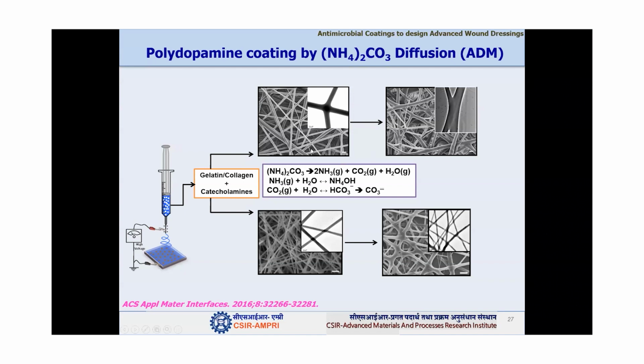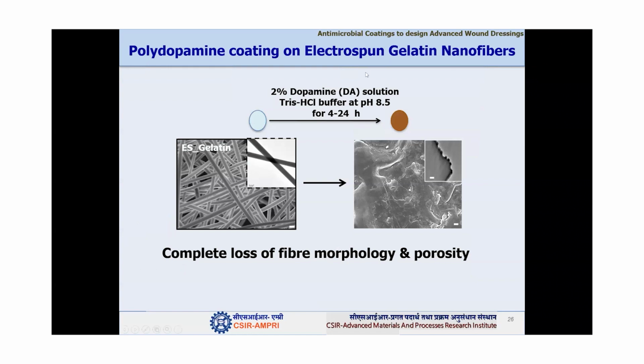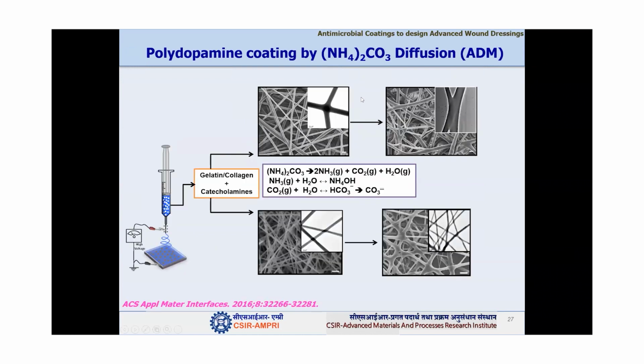Now we want to polymerize the dopamine into polydopamine, for which, as I have mentioned, we need a high pH condition, an alkaline medium. For polymerizing dopamine to polydopamine, we need a pH of 8.5. So instead of using liquid media to attain the pH, we used a vapor phase method. We put the dopamine-containing nanofibers in a desiccator where we have ammonium carbonate. So what reactions happen in the desiccator? Ammonium carbonate gives rise to ammonium hydroxide and carbonate ions in the chamber, and this creates an alkaline medium, and the pH is around 8.5 again.